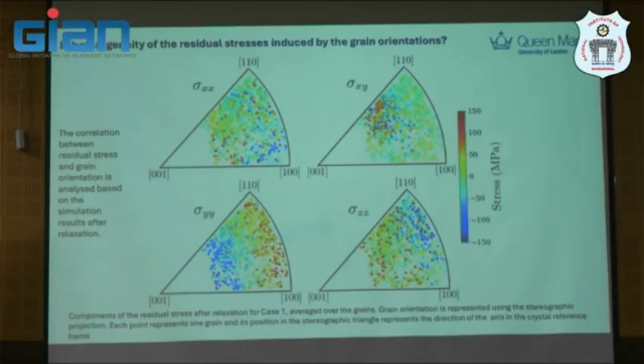That means if it's linked to grain orientation, you can impose some way to tailor the grain texture, it's the same thing, right? How can we get the texture correctly at the beginning? That's why we can control residual stress. And this is how they map from experiment. You see a band of soft, I would say, compressive and tensile grains at different locations. The correlation of this may give further insight from simulation and experiment to change the printing practice, or find some way to control grain orientation and texture, for example.